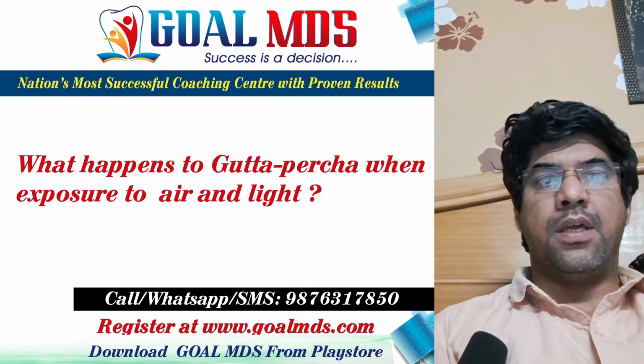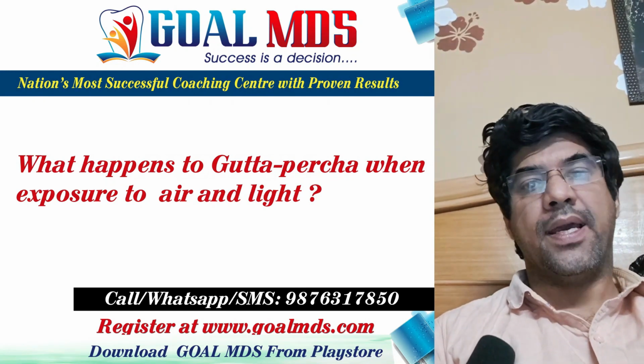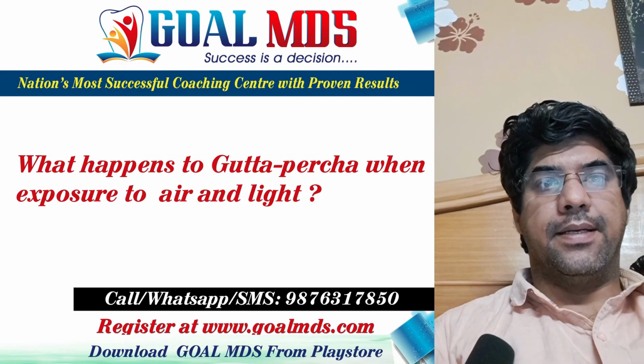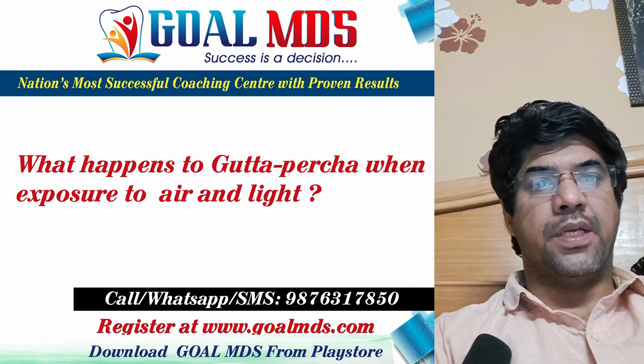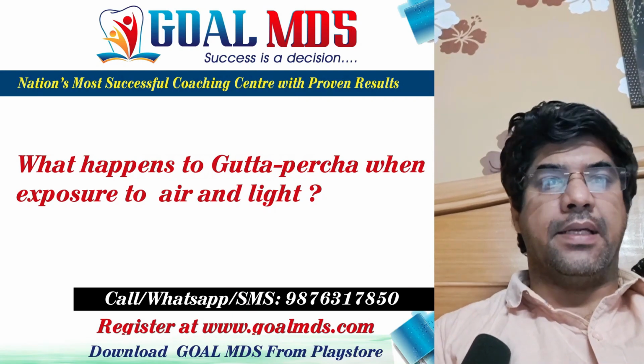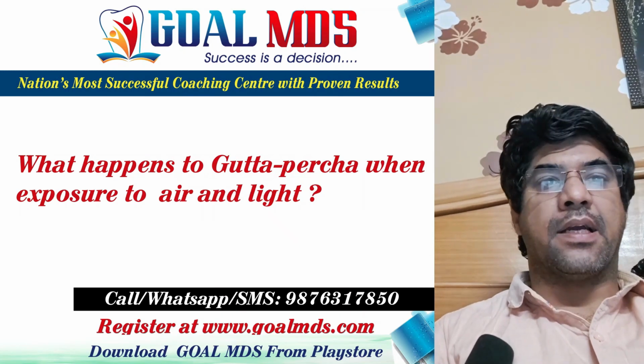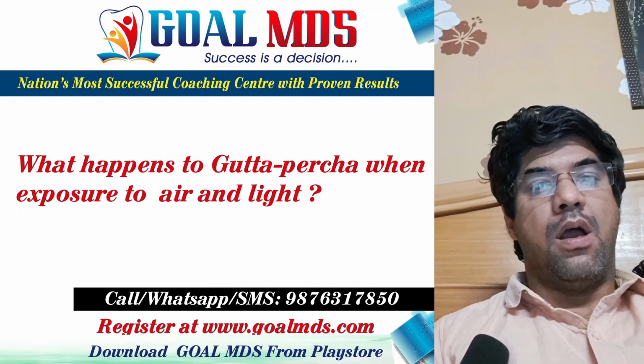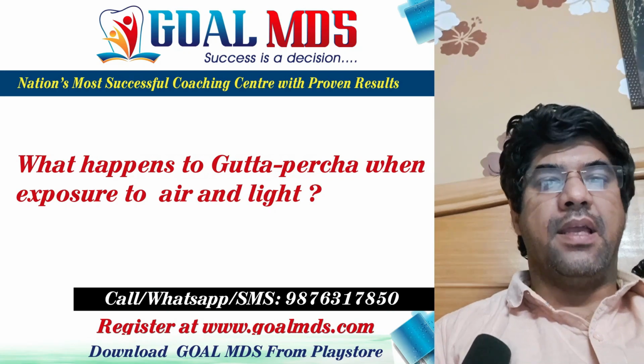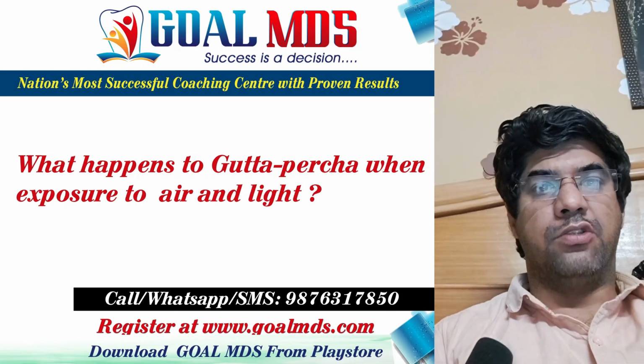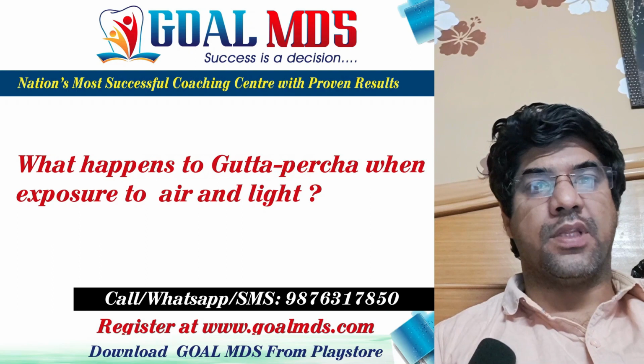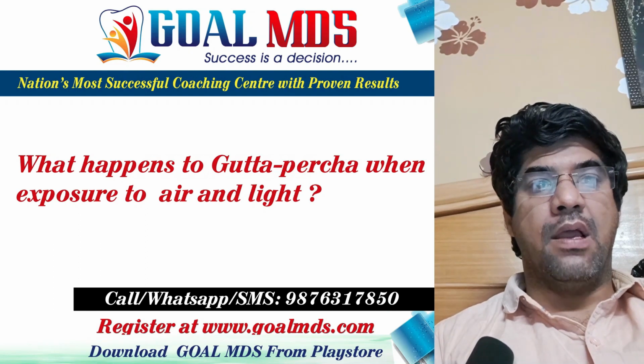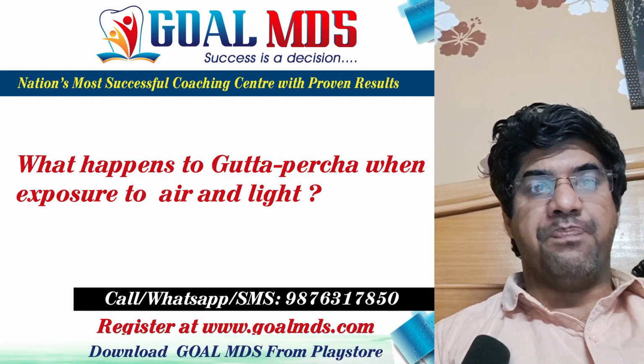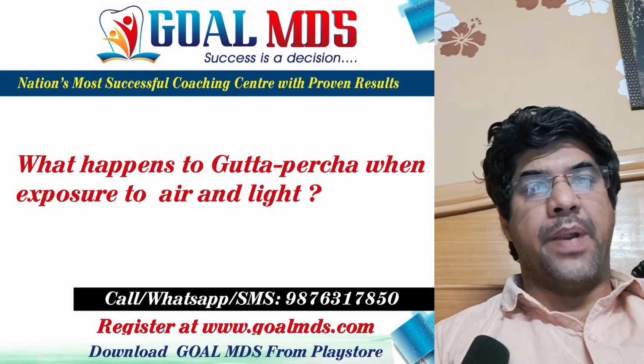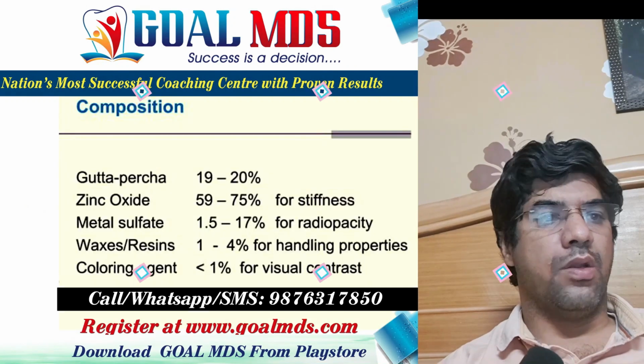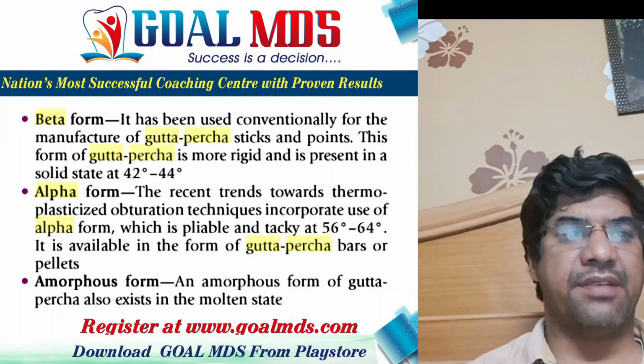So what happens when Gutta Percha is exposed to air and light? On exposure to air and light, you will notice that the Gutta Percha can become oxidized and brittle. That is why we have to store it in a cool and dry place, that is a refrigerator, for better shelf life.